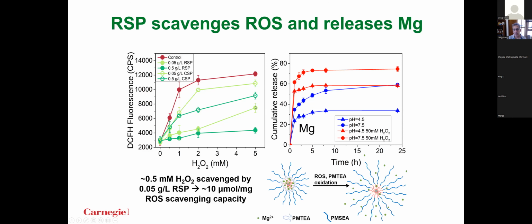Here's the same concentration of polymer, but our reactive one. So there's a big drop between the two. And then if we go to a higher concentration, this is our control polymer that is scavenging a little bit of stuff. But this is our reactive polymer at, in this case, 0.5 grams per liter. And you can see that it's pretty much scavenging all of the ROS in the system. So it's doing its job. And this is in vitro, not in the plant yet, although I'll show you in a minute, we have some data for inside the plant.